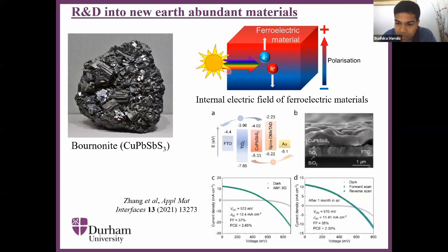Again, research into this material is at a very early stage, but just this year, they have demonstrated a working device with an efficiency of around 2.7%. This is still far below the 20% efficiency of silicon and commercialized thin film solar cells. But nevertheless, these are early days, and certainly these kinds of materials show a lot of promise.